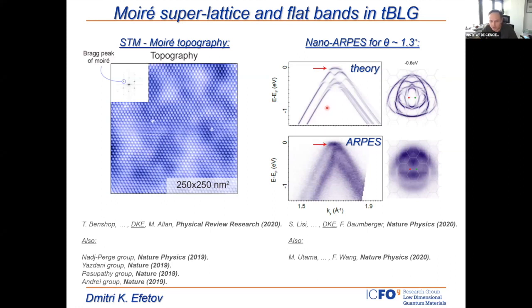And secondly, as I mentioned, the band structure becomes really strongly renormalized when we go close to this so-called magic angle of 1.1 degrees. So here I show the theoretical band structure of twisted bilayer graphene if we consider a twist angle of 1.3 degrees. What's really striking is that the Fermi surface gets extremely complicated, but also the bands break up into different sections, and specifically at zero energy we get these ultra-flat bands, which are separated by band gaps to higher order bands. And this can be seen in nano-ARPES. These are, for example, experiments done by our collaborators Felix Baumberger in Geneva, and we can see those ultra-flat bands and also energy gaps forming to higher order bands.